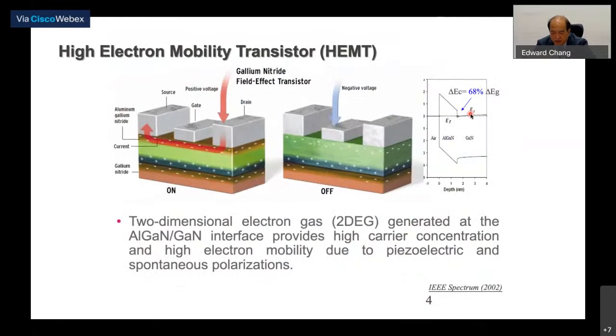First, let me give you some idea about gallium nitride HEMT in case you do not know too much about it. In contrast to silicon devices, the gallium nitride HEMT semiconductor device does not need any dopant. In this HEMT device, we have gallium nitride and aluminum gallium nitride to form a high band gap and low band gap material to form the 2D electron gas. This 2D electron gas has a very high carrier concentration due to the surface state, and very high electron mobility, which gives you very high current. And mostly the material has very high piezoelectric and spontaneous polarization effects, so that can generate a high internal electric field within the material.